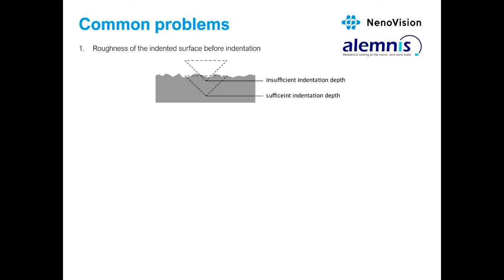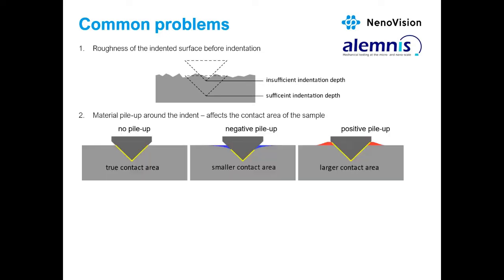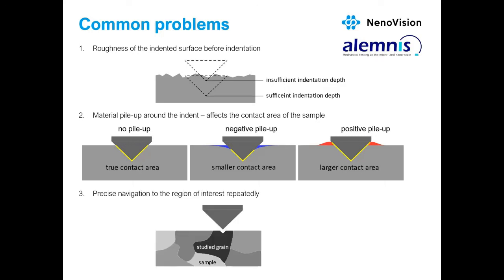Anyway, there are some difficulties with real nanoindentation experiments. It is nice to know the minimal feasible indentation depth, which we can find by measuring the roughness of the surface before the indentation. Then, we need to measure the pile-up effect, which can influence the hardness computation because the contact area of the sample with the tip is changed. The third one is really time-consuming and actually challenging. If we have different devices, it's really hard to precisely navigate, especially when we need to repeatedly localize the indents.